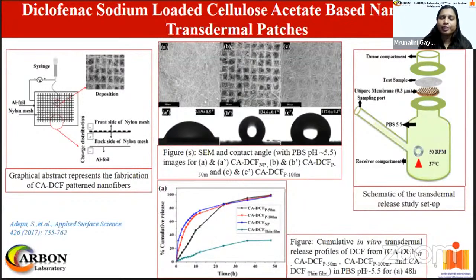We loaded diclofenac into cellulose acetate nanofibers, which are hydrophilic in nature and would give a fast initial release. Tuning the surface wettability would give slower release. Thus, a novel and facile concept of micro-patterning of nanofibers using nylon meshes was introduced. The drug-loaded nanofibers were deposited over micro-patterned nylon meshes of different thread spacing, 50 and 100 micrometer. It was observed that the fibers deposited over the 50 micrometer spaced nylon mesh showed lower wettability compared to other depositions, including non-pattern mats and thin films.